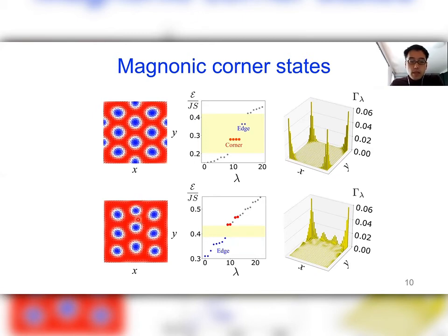We can actually see this just by looking at the antiskyrmion in the middle column, slightly displaced vertically from the center of the magnetic unit cell. In contrast, the repulsion between fractional antiskyrmions and the antiskyrmions in the bulk restores the nicely symmetric magnetic unit cells even in a finite sample. And this is why we have symmetry-protected magnonic corner states, as we show here.